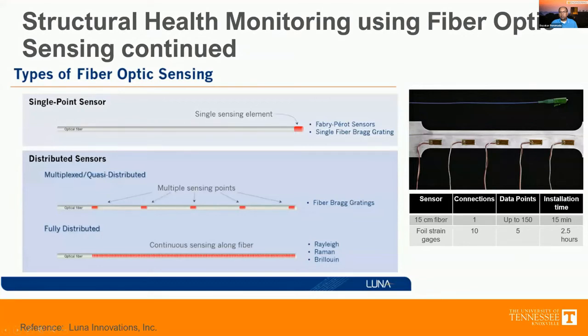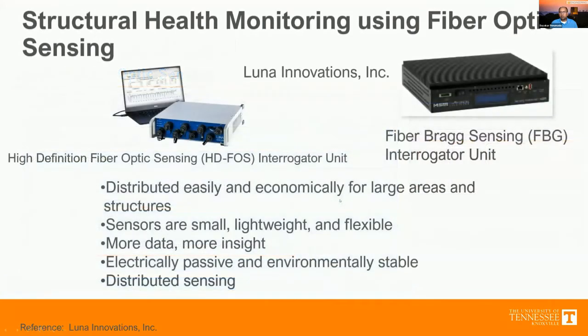Now, if I were to replace that with one fiber optic sensor, where all I have is one connectivity which sends a laser of a certain wavelength that traverses the fiber, the entire measurement system relies on just this one end connector. We now have up to 150 strain gauge sensing points on this one fiber optic sensor, and the installation time is probably even less than 15 minutes. So naturally, anywhere we want a large number of measurement points without having to use a lot of interconnected cabling, and ensuring that they can survive harsh environments, fiber optics makes a lot of sense.